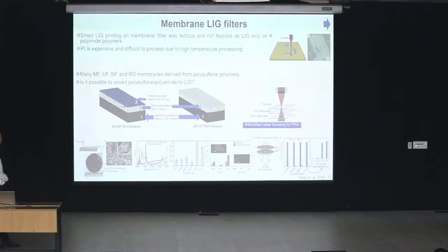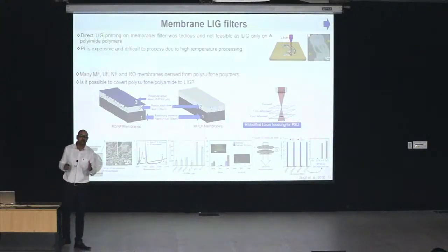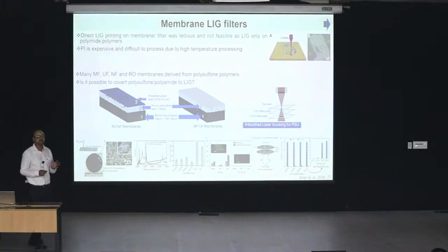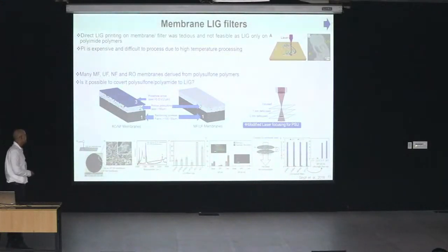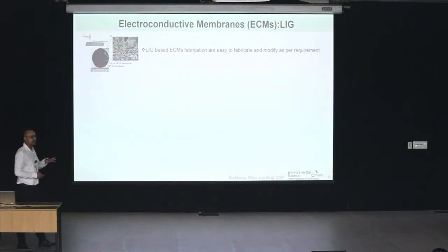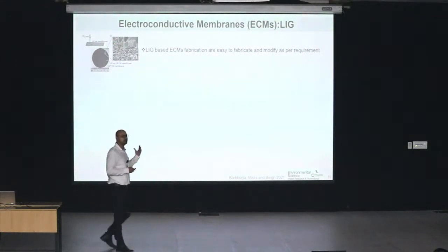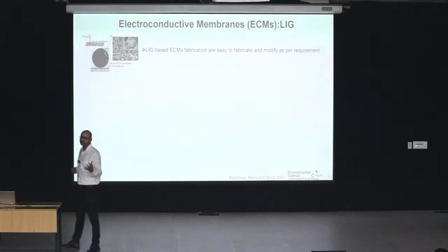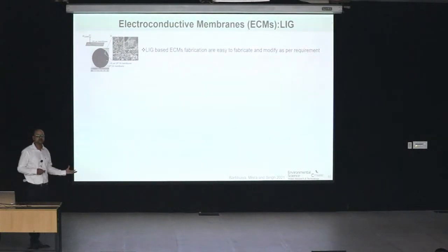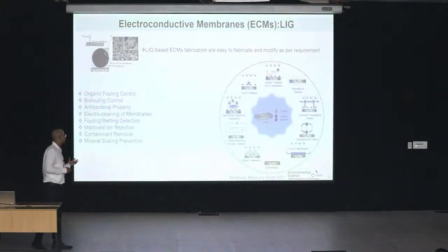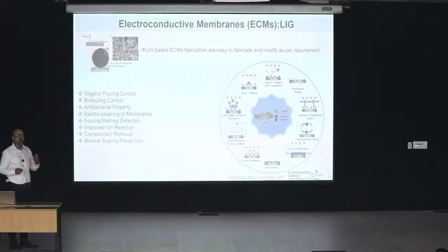And we have used different kinds of ultrafiltration membranes. We have converted them into laser-induced graphene filters, and we have performed several sets of experiments in a flow-through manner. The antibiofouling properties were all equally good or even better, because polyether sulfone has a lot of sulfur in the moiety, and when laser converting into graphene, these graphenes are sulfur doped. So they have shown even better electrocatalytic property as compared to normal polyimide membrane. So this has shown a path for how in a single step we can convert these membranes and make these filters electroconductive, which is a graphene-based filter, and then we can utilize different kinds of electroconductive properties to make a new generation of membrane.